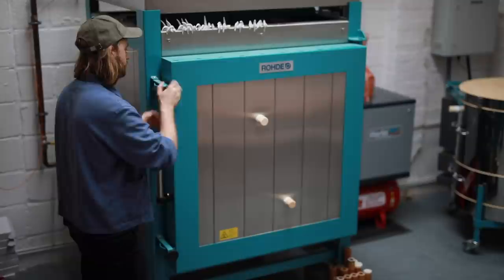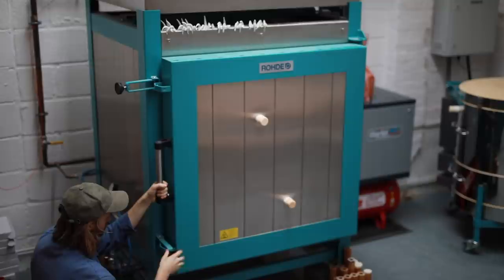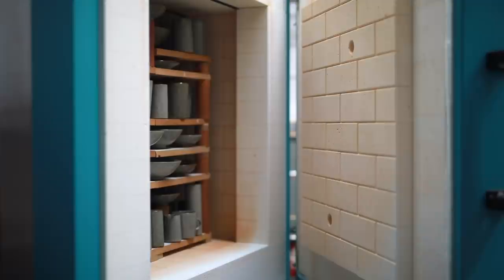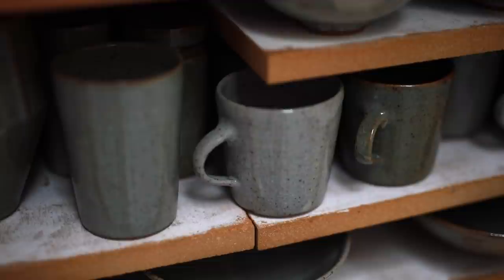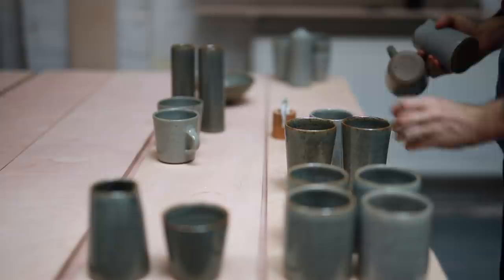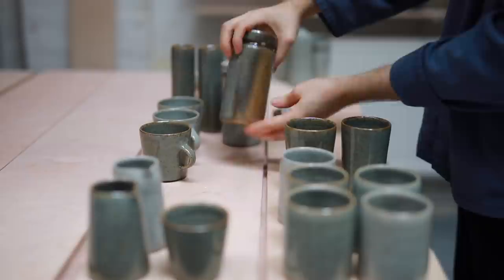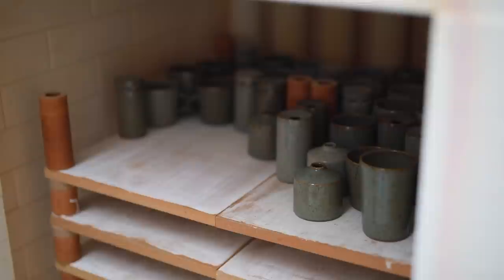About a day and a half later, once the kiln has cooled down to about 150 degrees centigrade, I can crack it open. This is always an extremely anxious moment, as during the entire firing process you haven't actually been able to look inside and see what's happening. All you see are white-hot shiny pots, so it's very difficult to gauge what the actual surfaces are doing. But at this moment, when you finally crack the door open, all is revealed. The soft tinkling noise you can hear is the sound of the glazes contracting over the stoneware clay body beneath — this doesn't continue for long, but still occasionally pots in my house will randomly tinkle months or even years after they've actually been fired. These spiky things I'm removing now are the pyrometric cones. Every single one of these pots is carefully inspected as they are removed — there's so much to go over, and it can take hours to really have a good look at everything. I'd say I have about a 95% or 98% success rate with this kiln, along with a few occasional surprises, such as slightly oxidised pots and other oddities, which are always such fun to discover.